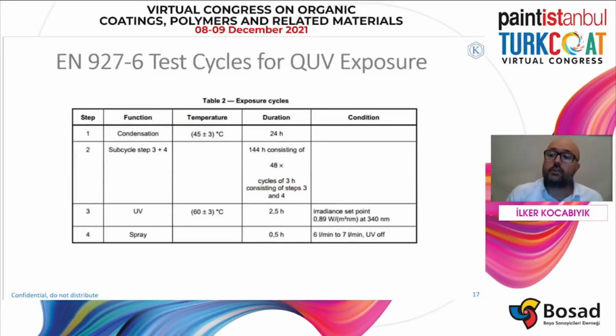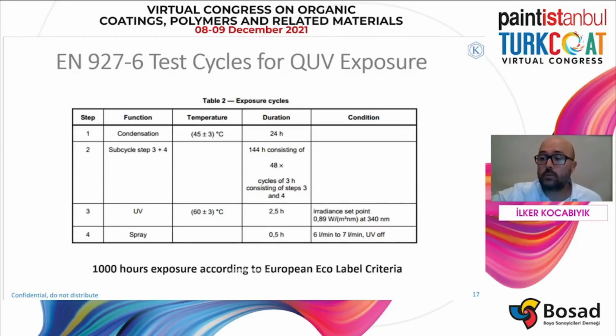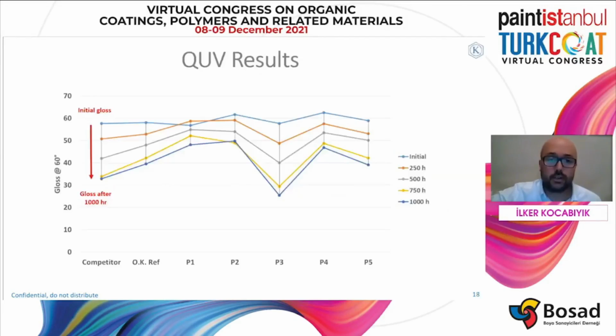QUV testing according to EN 927-6 is used as an accelerated test to predict the behavior of paints under outdoor conditions. Gloss paints are applied on pine wood and dried for at least 7 days before testing. Exposure time was 1000 hours as the guidance of European Ecolabel criteria.